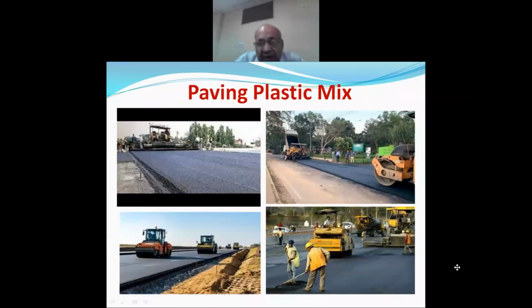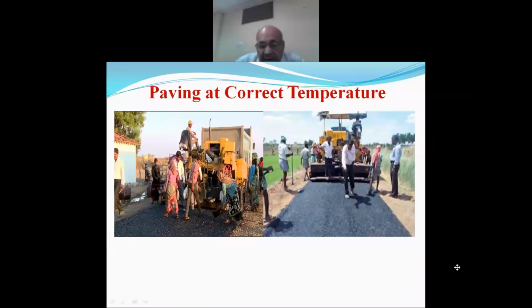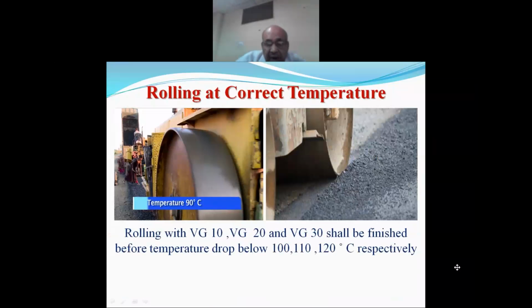Mix at mixing plant 140 to 160 degrees centigrade, mix at laying site 130 to 150 degrees centigrade, rolling at laying site 115 to 135 degrees centigrade. So there is a requirement of about 15 degrees higher temperature for rolling of the plastic modified mix.